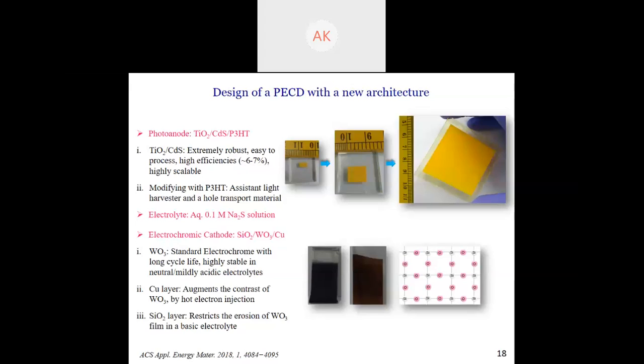But in this work, we have aimed at achieving a transmittance modulation that is more than double what was achieved in 1996. It was slightly higher than 20%. So we will definitely try getting more than 40%. For that, we have added a thin copper layer below the WO3 layer so that it augments the contrast of WO3 by hot electron injection. Similarly, on top of WO3, we have added a SiO2 layer, which will restrict the erosion of the WO3 film in a basic electrolyte. Now, SiO2 as a passivation layer has been previously used in a lot of other QDSC reports as well.